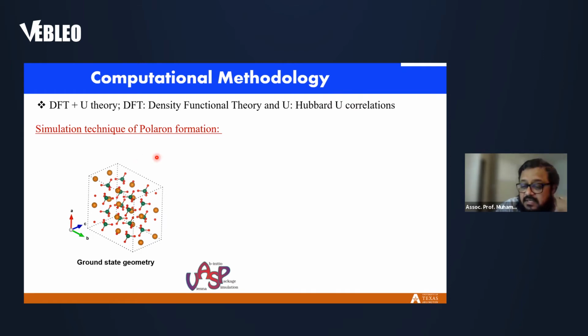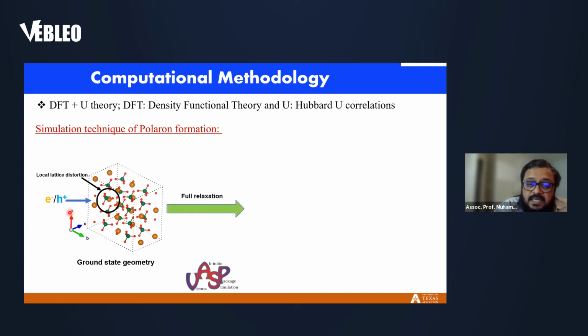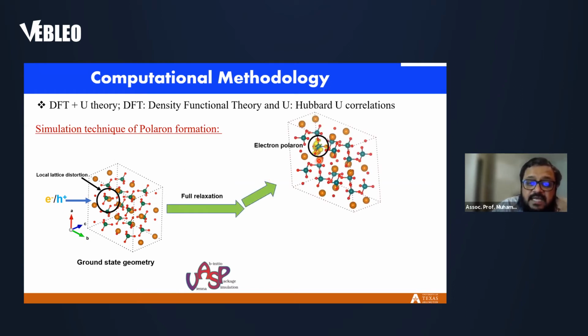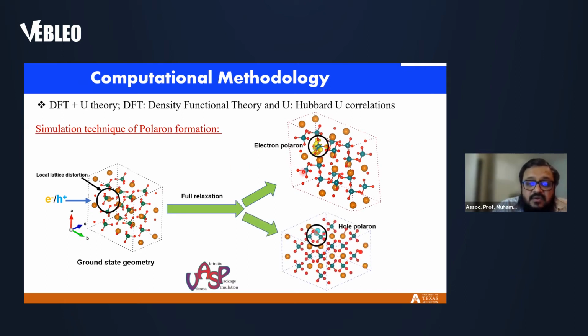Then the way we model polaron is that if we have a unit cell, we can pick a site on which the polaron can be formed and add an electron or hole, depending on which polaron we want to model, and then add a small perturbation on that site to ensure that the electron or hole, at least initially, resides on that site. Then we do a complete full relaxation. Even after the relaxation, if the charge density is still found to be localized on that site, if it is an electron, then it's an electron polaron, or if it is a hole, then it's a hole polaron. All the calculations for this presentation were done with the VASP ab initio code.